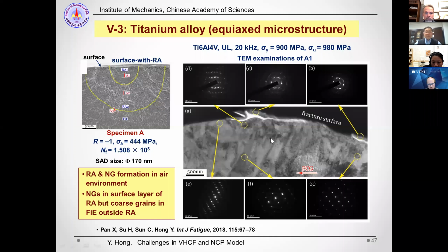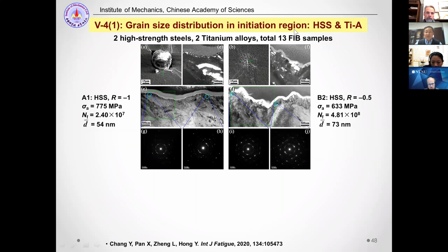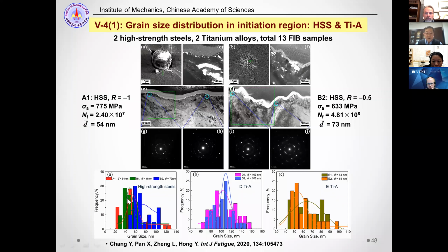And the fourth one is grain size distribution in the initiation region of high strength steels and titanium alloys. We tried to measure a number of samples. This is the case of high strength steels, and we also observed the titanium alloys to reveal the grain size distribution. This is for high strength steel, and this is for titanium alloy with duplex microstructure and with equiaxed microstructure. For high strength steel the grain size is between 50 and 70 nanometers, for titanium alloys with duplex microstructure about 100 nanometers, and 50 to 60 nanometers for equiaxed microstructure.